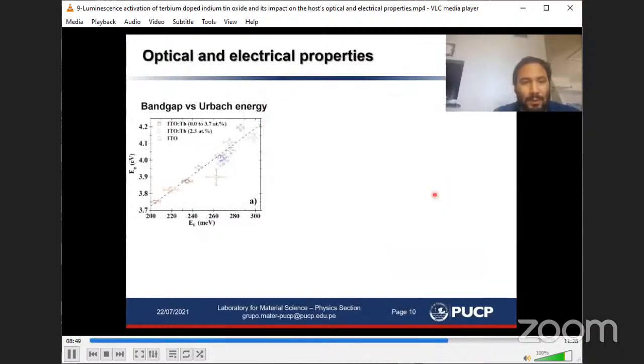So concerning the optical properties, we measure the optical bandgap and Urbach energy, and in this plot I'm relating them. Here we have bandgap versus Urbach energy for samples with different terbium concentrations, samples with terbium but different annealing treatments, and samples without any terbium but different annealing treatments. And we observe the same trend: the bandgap increases when we increase the Urbach energy.